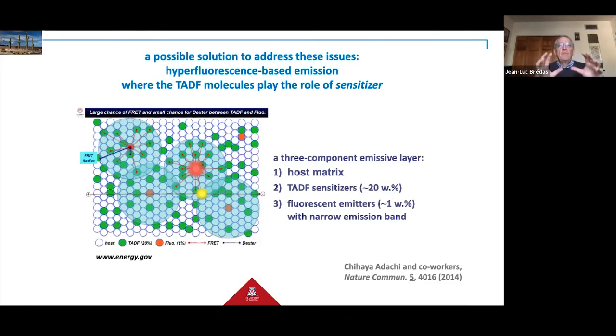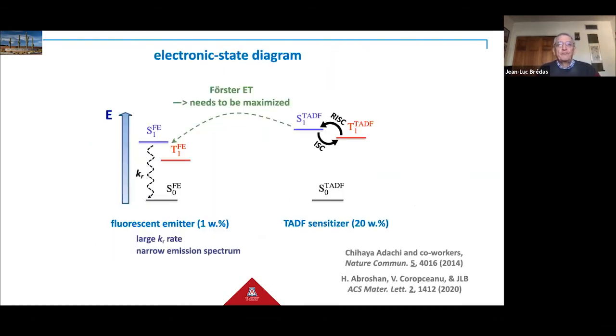And the idea here is to have an emissive layer that has three components: a host matrix, TADF molecules that are now used as sensitizers, and then fluorescent emitters into which we want to funnel all of the excited states, fluorescent emitters that have a narrow emission band, so high color purity, and very fast decay.